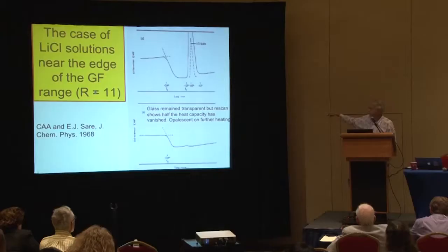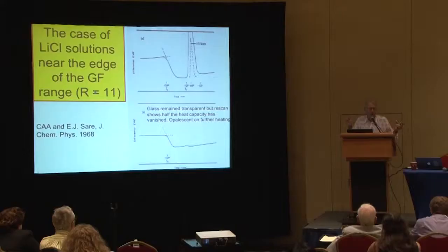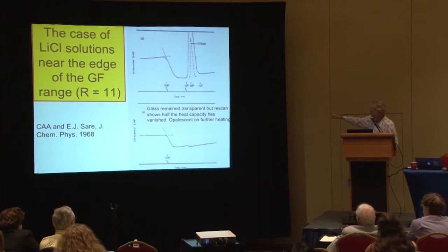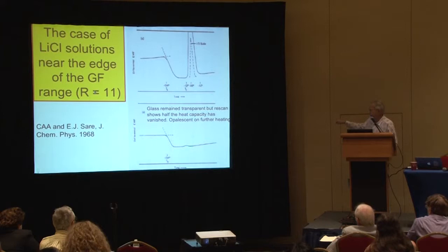Now, what's happened? Unlike most other glass-forming substances I'm familiar with, it's generated, for some reason, this tremendous host of nuclei, all of them far below the wavelength of light. And those nuclei have then grown a little bit, but not much, because the liquid is very viscous at this point near the glass temperature, so it can't flow. And so there's a giant increase in pressure, and that's what blows the glass apart. And then after a little while, these nuclei grow to the wavelength of light and give you the opalescence, and then you can see them. And if you rescan this now after this has happened, but before it's gone white, then you see the same thing, slightly different temperature, and only half of the magnitude because all of the water's now gone. You've just got the lithium chloride water solution left, and a tiny rump of what you saw before.